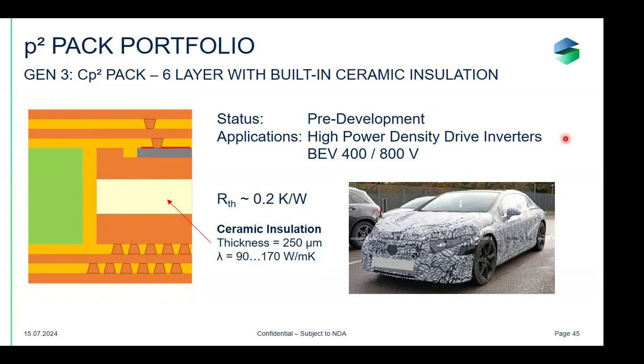So in the generation 2, we are already making inverters for up to 850 kilowatts. But if you want to have these 850 kilowatts in a very, very small space, then you have a very high power density, and then you have to minimize the thermal resistances as well as possible. And if it comes to very high power densities, we think the generation 3 will be the technology of choice. It's also going into battery electric vehicles at a voltage of 400 and 800 volts. And maybe in the future, even more than these 800 volts.